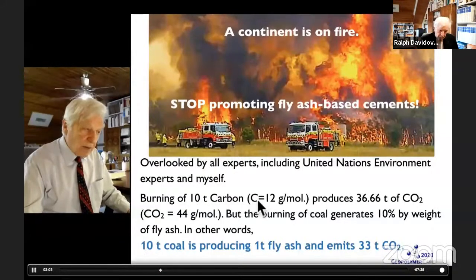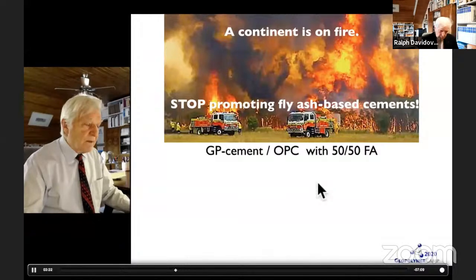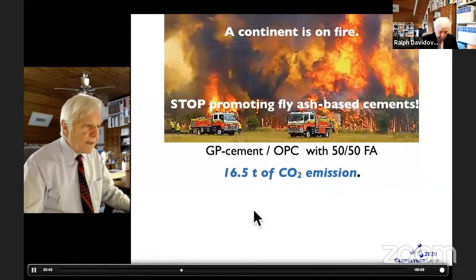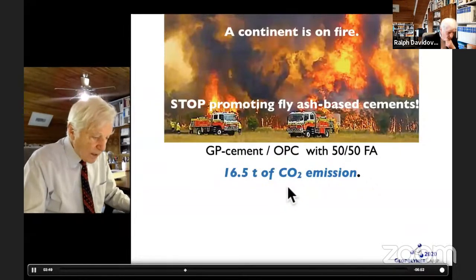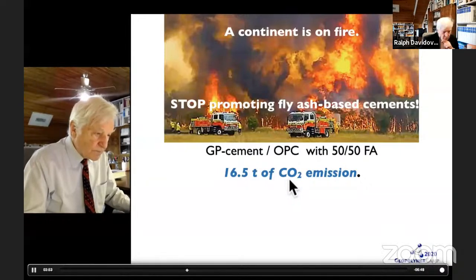The burning of 10 ton carbon, which has 12 gram per mole, produces 36.66 ton of CO2. But the burning of coal also generates 10% by weight of fly ash. In other words, 10 ton of coal is producing 1 ton of fly ash and emits 33 tons of CO2. If we take geopolymer cement or a Portland cement that is blended with a 50% fly ash, then we have to add 16.5 ton of CO2 emission to what has been calculated.